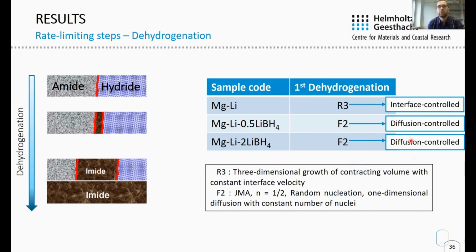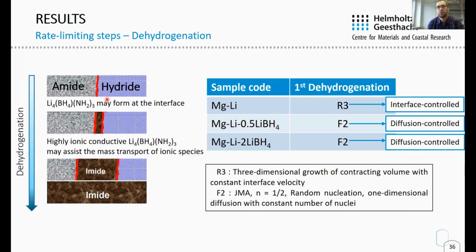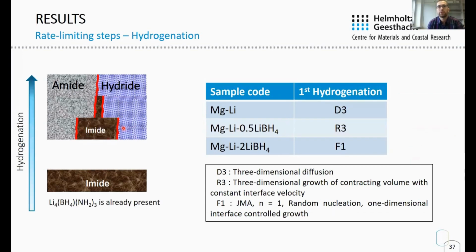In the presence of lithium borohydride, more stable dehydrogenation products are obtained at the amide-hydride interfaces by exothermic reaction of lithium borohydride with lithium amide to form Li4BN3H10, and this accounts for the change in the rate limiting step. Once this phase is formed, it may help the mass transportation of the ionic species.